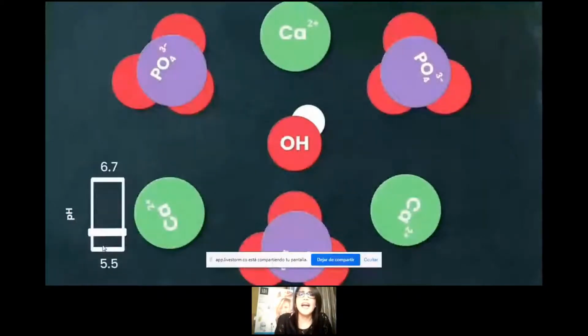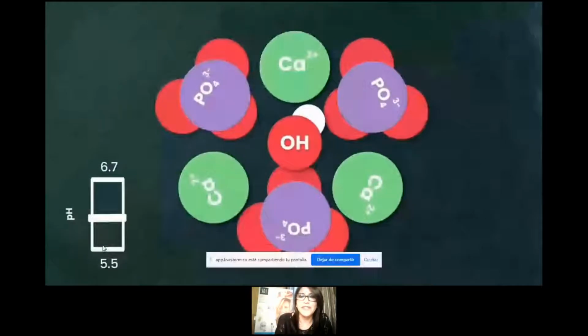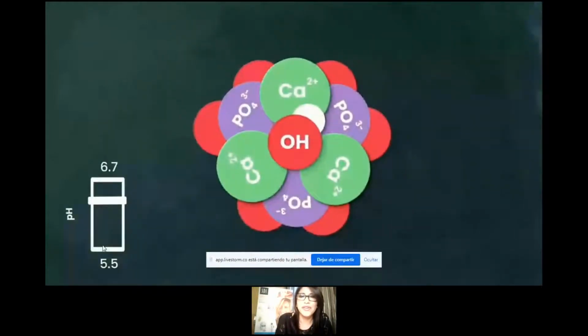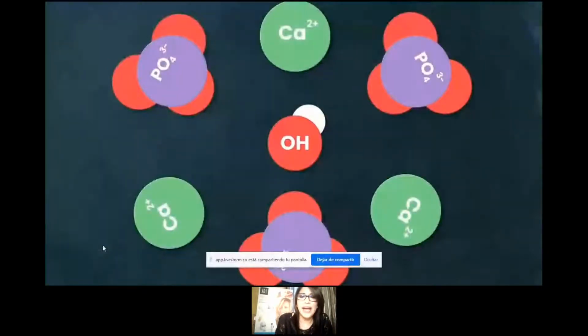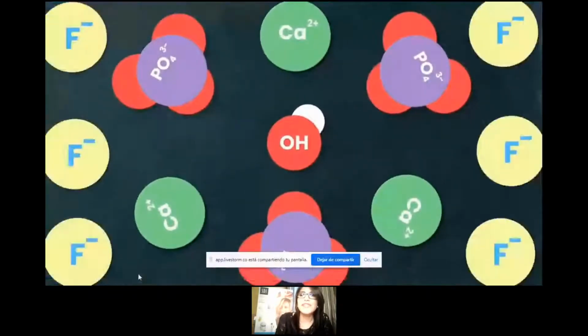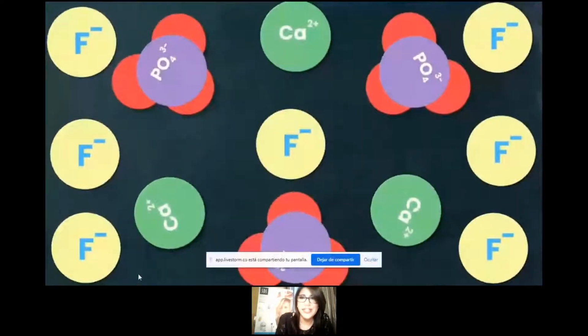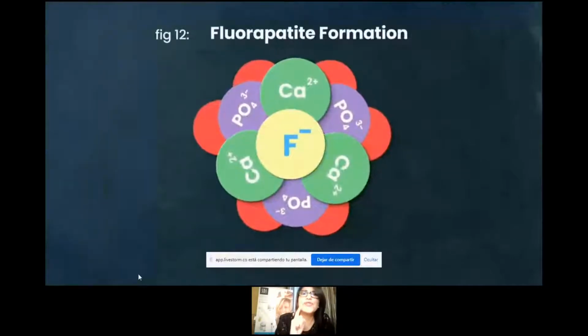And what is the best remineralization material? If we are losing calcium and phosphate, and we want to have again a hydroxyapatite crystal, what kind of material are we going to ask for? We're going to ask for fluoride for remineralization. But what does this fluoride need for fluorapatite formation? It needs calcium and phosphate. If you have fluoride ion and you don't have calcium, you are not going to have remineralization. Remineralization is not the fluoride. Remineralization is the fluorapatite formation.